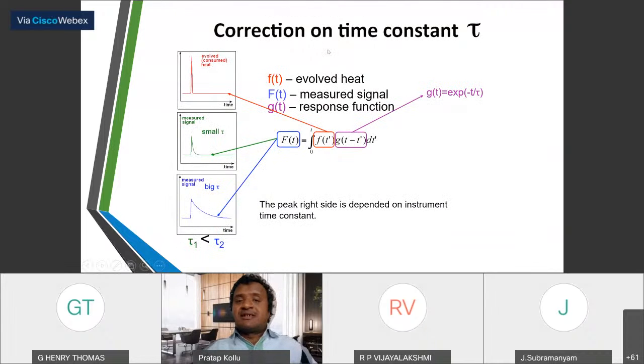So look at the other correction. It is time constant. So this is evolved heat, the red one. This is the measured signal when time constant is small. So this is the measured signal when time constant is very large. So how do you correct it? So measured signal is equal to the integral from 0 to t of evolved heat into g of t. So it is an exponential function of time by the time constant.